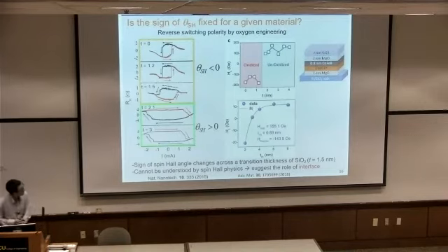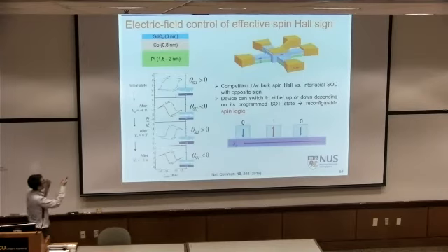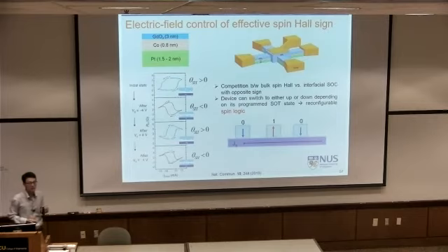So recently we tried to mimic or repeat this experiment in one device. So we use gadolinium oxide and the cobalt platinum bilayer. And gadolinium oxide is known to have a huge oxygen reservoir. By gating, you can push your oxygen into cobalt, and you can pull back, so you can oxidize and you can reduce back and forth depending on the gate voltage.